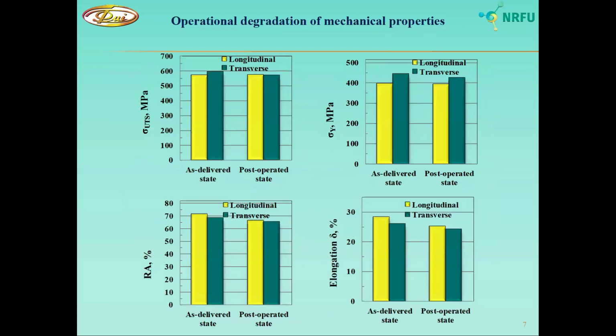An anisotropy of mechanical properties for all pipeline steels is a well-known phenomenon, and it's important to know whether long-term operation influences the anisotropy of mechanical behavior. Based on the presented data, we can see that the anisotropy of basic mechanical properties is insignificant for the studied steels, and the higher strength in the transverse direction compared with the rolling one is commonly observed for all steels. And in this case, we have a similar mechanical behavior, except for the operated steel, where the ultimate strength is the same in both directions. The plasticity characteristics for the operated steel are somewhat lower than for the delivered one, indicating operational changes in the material.